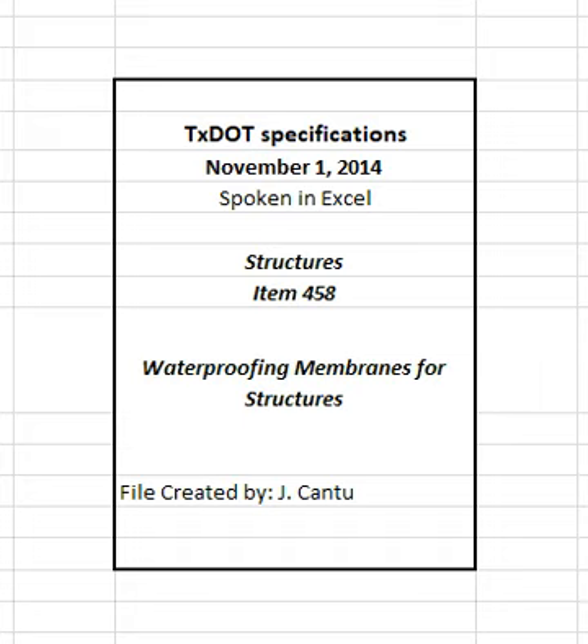Lay a 15 inches wide strip of cotton fabric on the first mopping while the asphalt is still hot and press into place. Apply subsequent moppings to completely cover and seal the cotton fabric. Make the end laps of the cotton fabric at least 12 inches unless otherwise shown on the plans.